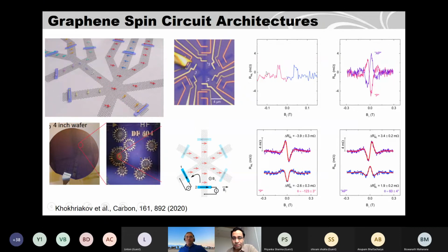Okay, so when you do spin valve measurement, you can do that, because this is in plane. But what we do, when you do Hanle measurement, actually it's a very small magnetic field with a perpendicular magnet. So that won't change the magnetization. But for your in-plane measurements in the spin valve, do you change the magnetic field angle accordingly, or do you keep the magnetic field angle constant, and then you measure between different electrodes? Yes, so the applied field here is constant in plane. We just sweep the magnetic field.